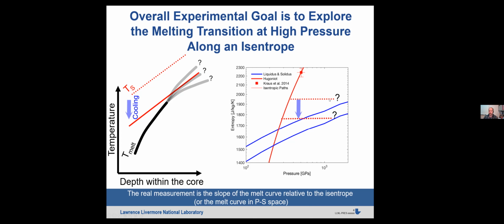So that allows us to map out the melting curve, where of course entropy is an extensive variable. So you have a liquidus showing the boundary between pure liquid phase and the solid plus liquid phase, and you have a solidus at the boundary between the solid plus liquid phase and the solid phase. So again, in these experiments, what we're trying to do is map out the melting curve in the pressure entropy space so we can understand how cores solidify, thinking back to this temperature depth space.